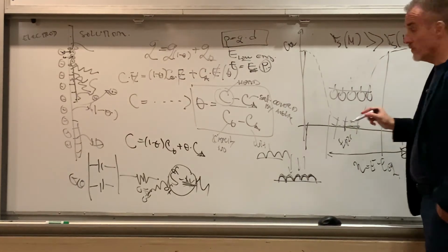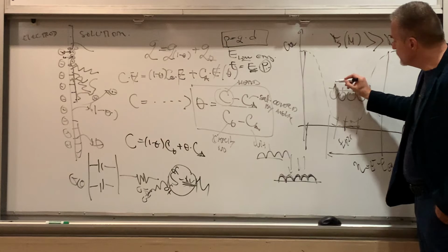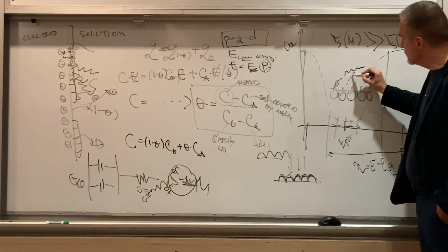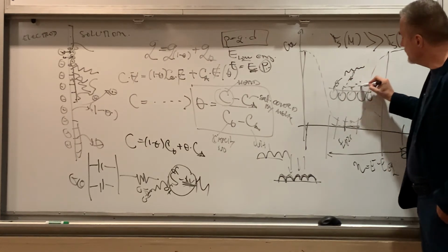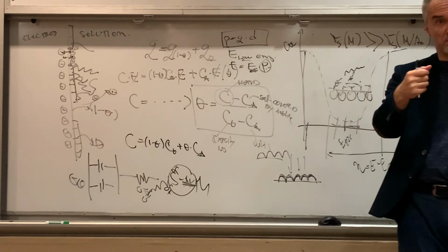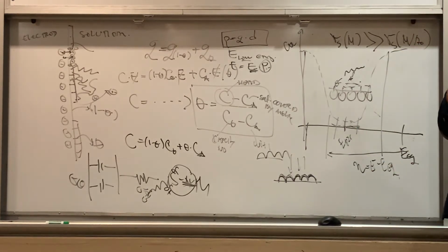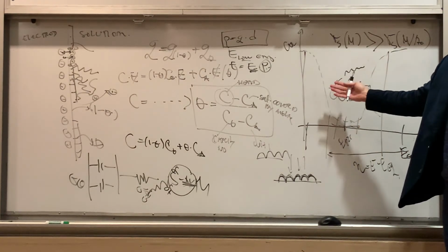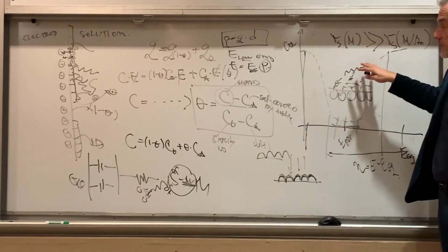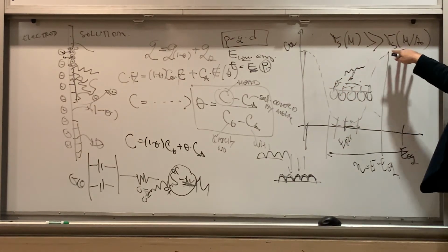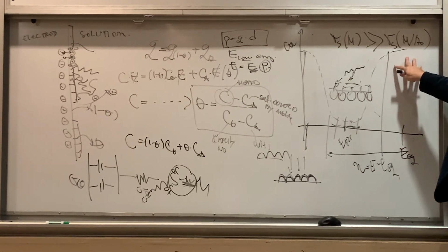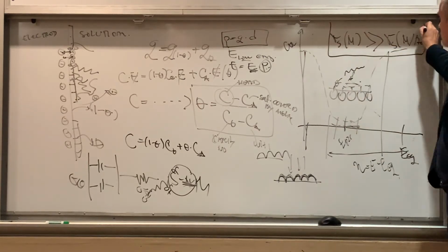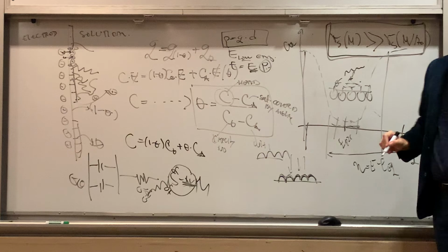Yet, when I have organic phase adsorbed, what happens is that some of these bonds will be saturated with this S, whatever, maybe this bond will be saturated with some oxygen from here. So there will be formed a lot of bonds with metal atoms, which will not look like broken bonds anymore of the clean surface, but will have a very different energy. And for that very simple argument, the surface energy of the adsorbate covered surface will be way, way smaller, okay? So that's the first consequence of the additives.